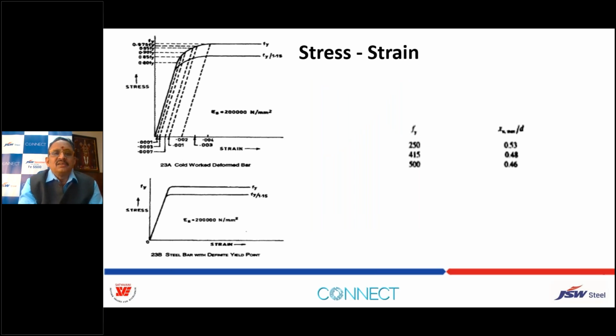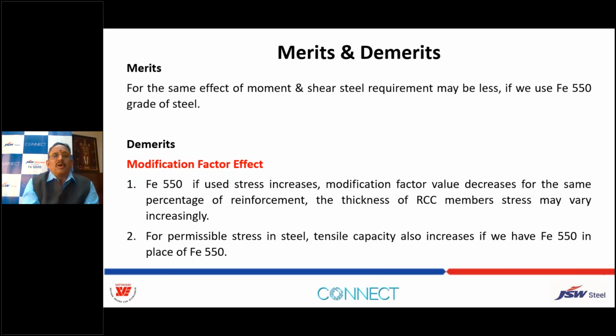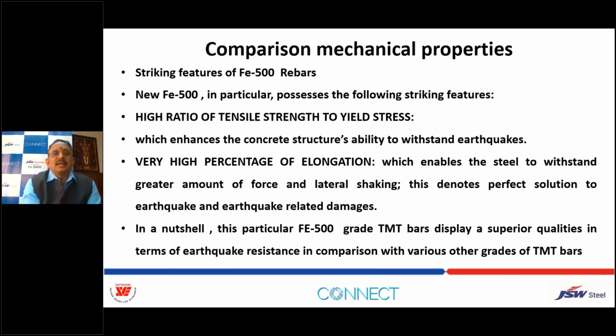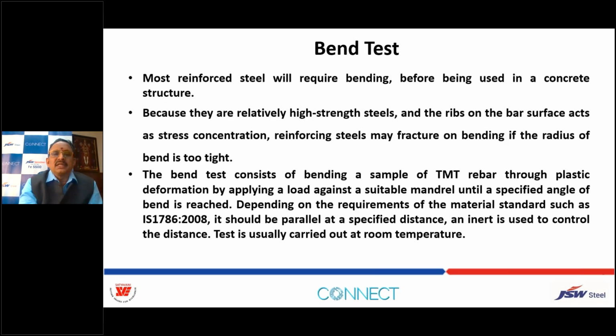And then stress strain curve for these high yield strength bars and HSD bars, IS 456 has given up to 500. And modification factor effect it will have on the stresses as well as the deflection criteria. So we all have to take care while using the high strength bars. And the mechanical properties, there is a high ratio of tensile strength to yield stress and very high percentage of elongation that is required for ductility, and TMT bars display superior quality actually for all these requirements.